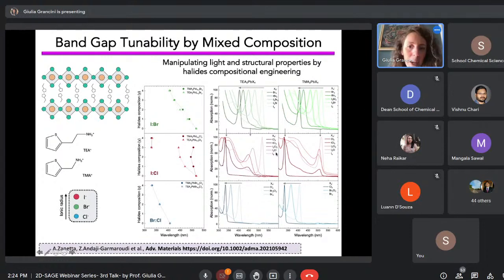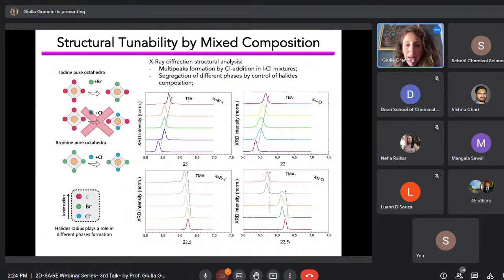But this does not happen when you mix iodine and chlorine together. It seems that you have two phases, no? A high band gap phase and a low band gap phase. Why? Basically because the radius of the halide plays an important role. The iodine and chloride are so different in radius that you cannot incorporate the chloride inside, and that's why you do have, in this case, two separate phases. In other words, you can, by controlling the halide composition, control the phase segregation in your material.